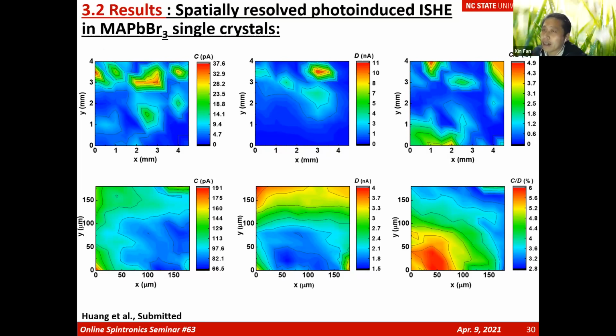So my specific question is, after you use this optical method to identify that hotspot, are you able to do some other spin-to-charge conversion measurement just on that spot? Well, I'm not sure whether I have such a spatially-resolved microscope, or maybe really by using photolithography, right? To detect the spin-to-charge conversion in that local spot. It's very challenging because these crystals are not like graphene, like 2D materials. They're very fragile to the solvents, typically acetone, which you need for photolithography. So basically, we cannot do any photolithography or any nano patterning to form the electrode on this local spot.